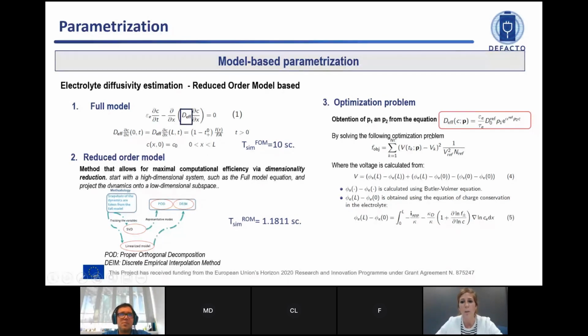Later, once we have these reduced models, we want to solve the optimization problems, and here what we aim to do is to identify the equation that correlates the electrolyte diffusion coefficient with the concentration. In this case, we have taken into account this specific equation from the literature, and what we want to do is to identify the P1 and P2 parameters. To obtain P1 and P2, we need to solve this optimization. As I said, it is basically minimizing the error between the simulated voltage and the experimental voltage, and the simulated voltage is obtained through the difference between the potential due to lithium stripping and plating, and also the ionic potential difference due to the concentration gradient.